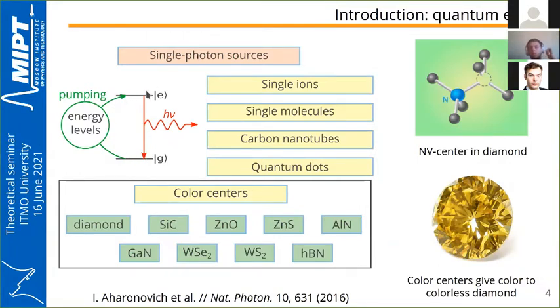From the first observation of single photon emission in 1977, various quantum emitters were proposed: defects in carbon nanotubes, single ions, single molecules, quantum dots. But the most promising are color centers in diamond, silicon carbide, and other wide bandgap semiconductors, which are point defects in the crystal lattice of the corresponding semiconductor. Color centers combine the properties of isolated atoms and solid-state sources, and unlike quantum dots, exhibit remarkable optical and spin properties at room temperature and above.